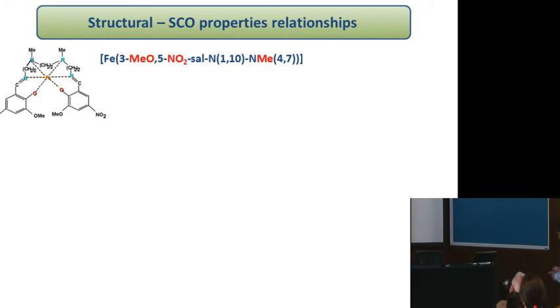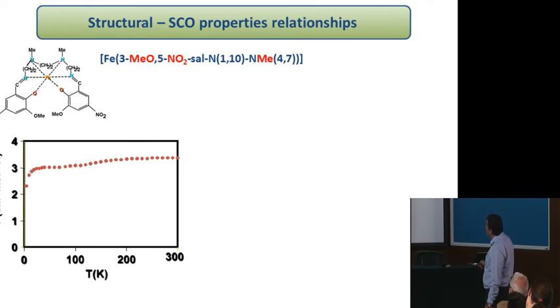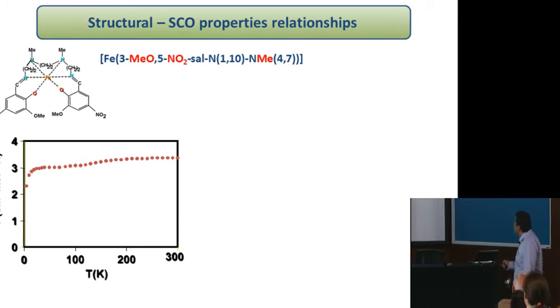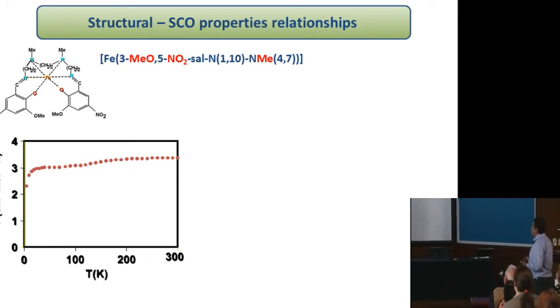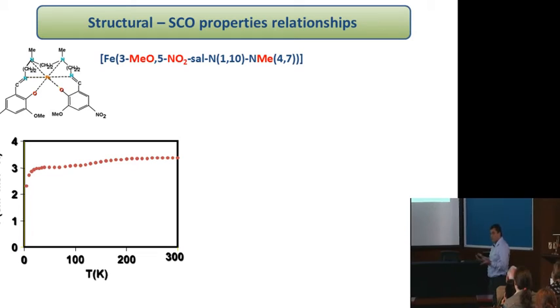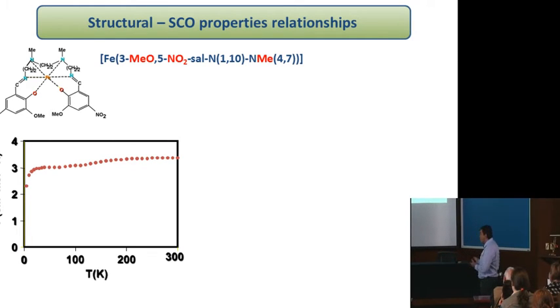Okay? So now, if you look at the spin crossover properties, we can observe small things here. Chi T equal to 3 corresponds to the high spin state. And what we observe is just a very gradual and very incomplete spin conversion. It's not a spin transition, it's a spin conversion, for these materials. So we try to correlate these properties with the structural parameters of this complex. This is the result of the structural determinations.